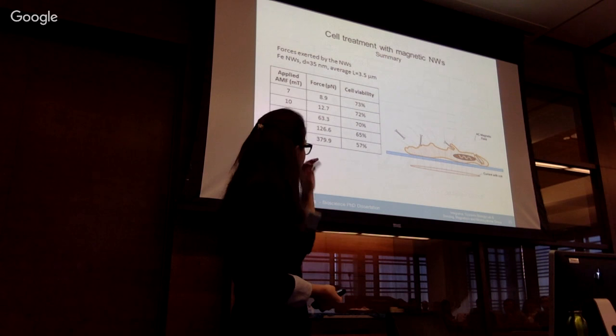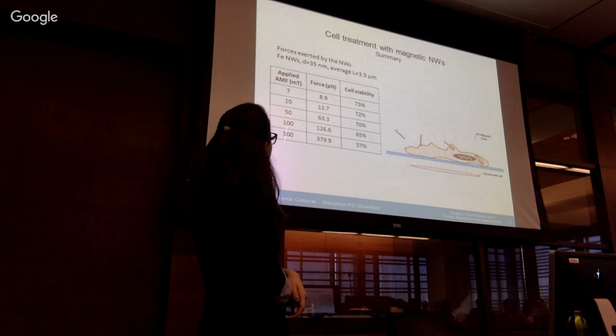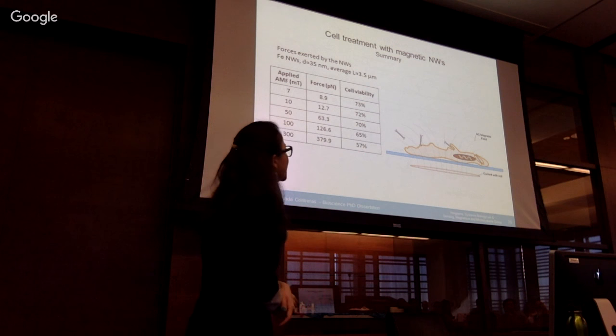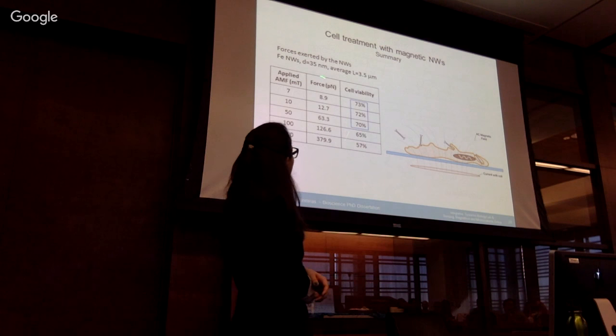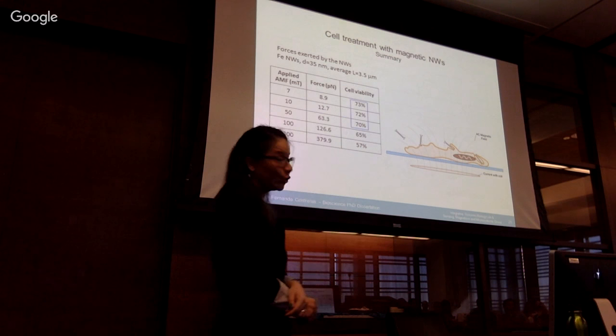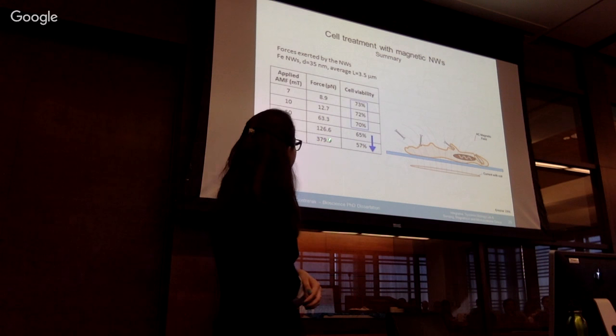I would like to summarize this latest experiment to see what I understand from this process so far. So here I'm just listing the different field intensities I used, the forces associated to them, and the cell viability I measured. These three values were not significantly different from each other, and even though I have a broad range of forces, these viability values didn't decrease regardless of this. However, if I did increase the force over a certain threshold, I start seeing this value significantly decrease.